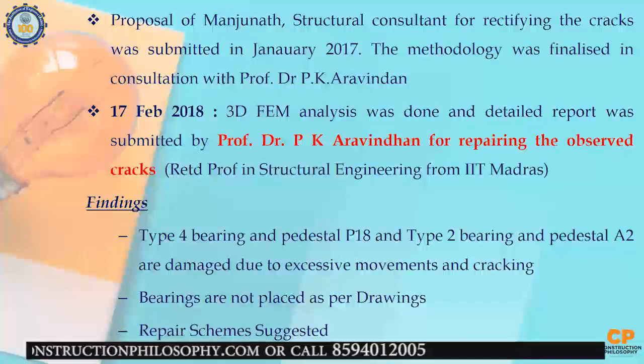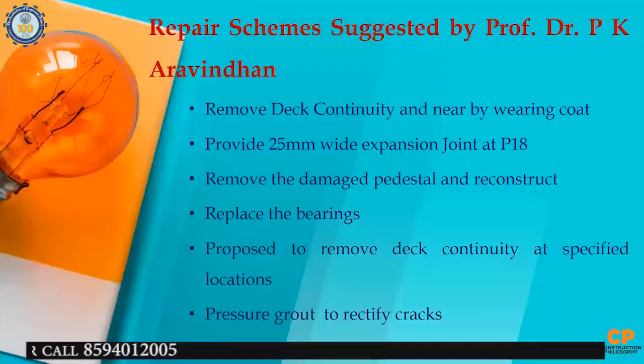So the findings were that type 4 bearings and pedestal P18 and type 2 bearing and pedestal A2 are damaged due to excessive movements and cracking. So the pedestal used was not good enough to take care of the movement. Bearings were not placed as per drawing, and a repair scheme was suggested. So this was the repair scheme suggested.